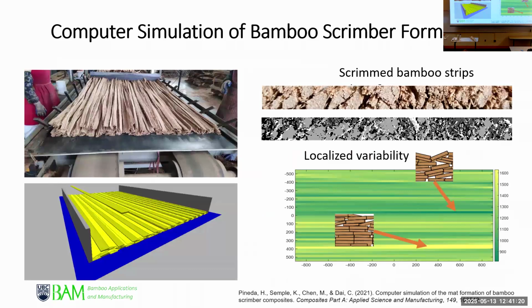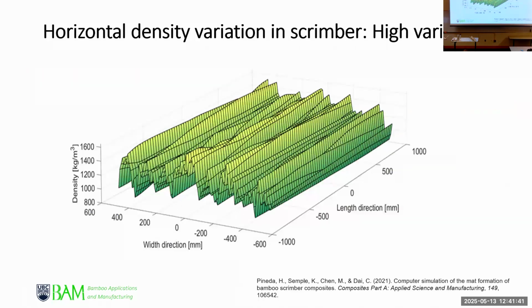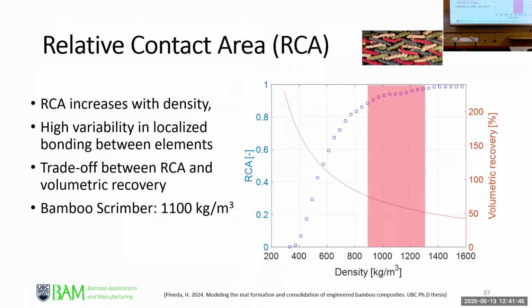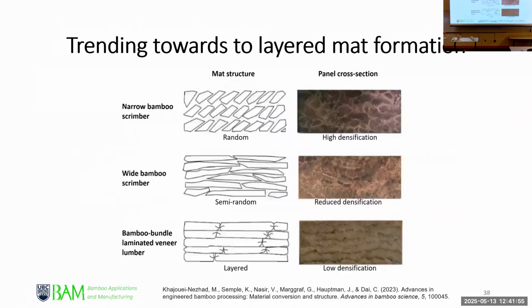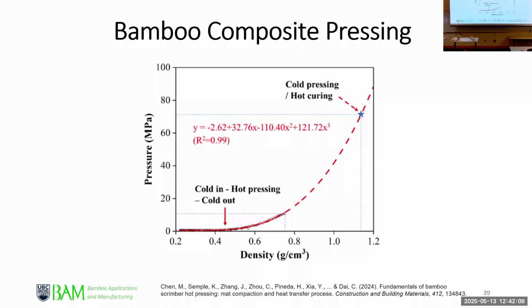And looking at the engineered bamboo, if you look at the strips, it's pretty much similar to what we see in the parallel manufacturing process. But the process is so manual, you can see that the operator is there hand forming them. And there's a lot of variation. So Hugo did a PhD to simulate this and found there's a lot of variation. And he predicted how one should densify the product to achieve the optimal performance yet getting the maximum volumetric recovery. So with that, we're proposing more of a layered system instead of a random material structure to allow the maximum recovery and optimal performance.